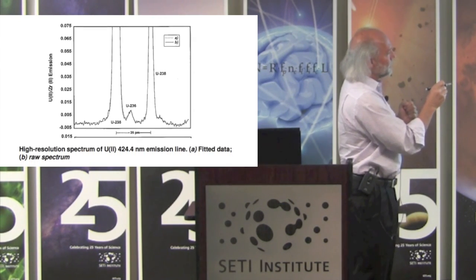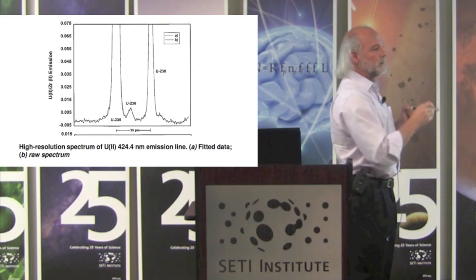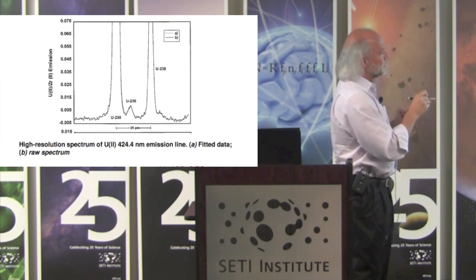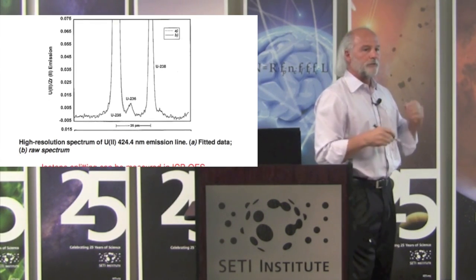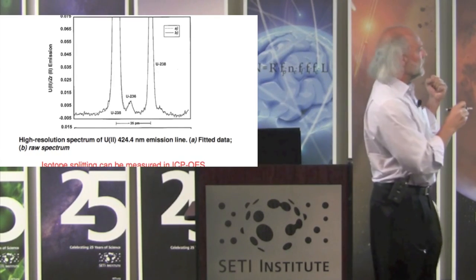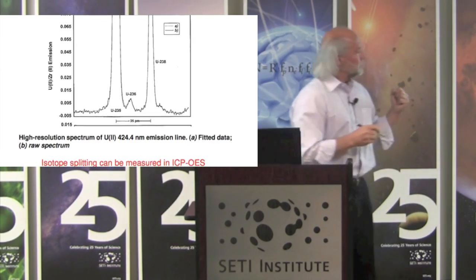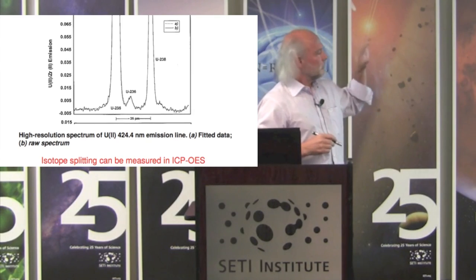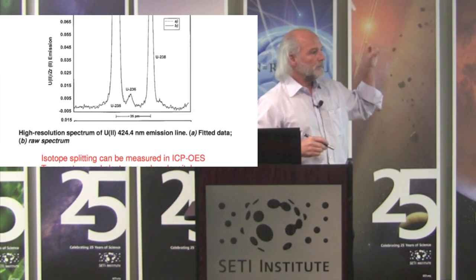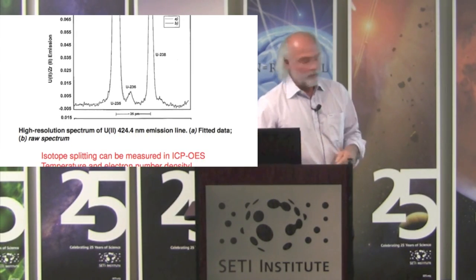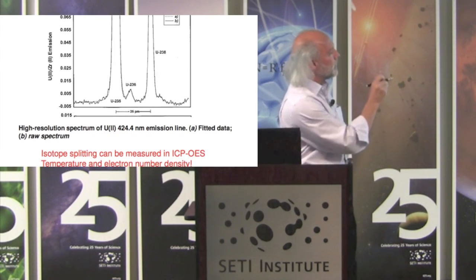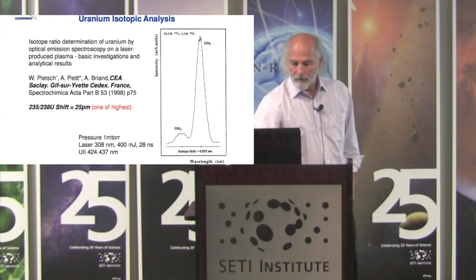But this line width will become larger than that shift, especially in a laser plasma, because in a laser plasma the electron number density can be orders of magnitude higher than in an ICP. So we haven't even looked at isotopes in these laser plasmas because of this reason. The shifts are very small and the lines are usually broadened.